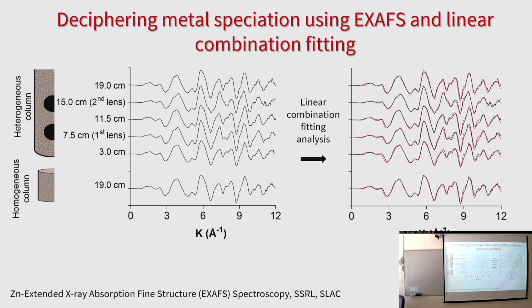And here I'm showing the results of our fitting. These red lines are overlapping very nicely with our experimental data, which proves to be a good fit. Our fitting showed that we needed 4 different zinc species to describe the various retention mechanisms: zinc layered double hydroxides, zinc associated with clay minerals, zinc complexed with organic matter, and a zinc sulfide phase. You see here, based on the colours, that we have a distinction between the sand and the lenses. The layered double hydroxides and clay minerals are found throughout the column in both the sand and the lenses. You can see that in green and in red.